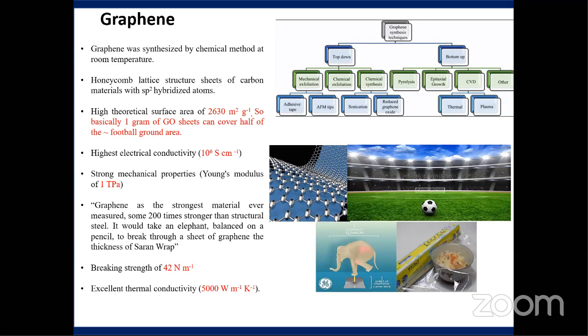Graphene is a honeycomb-like structure, sheets of carbon material with sp2 hybridized atoms. You can see why graphene structured material has unusual properties. The reason is its high surface area. You can see here the graphene sheet can cover half of this football ground. That's a good example. It also has the highest electrical conductivity, 10 to the power of 6 Siemens per centimeter, and strong mechanical properties. How strong is graphene? Graphene is the strongest material ever measured.